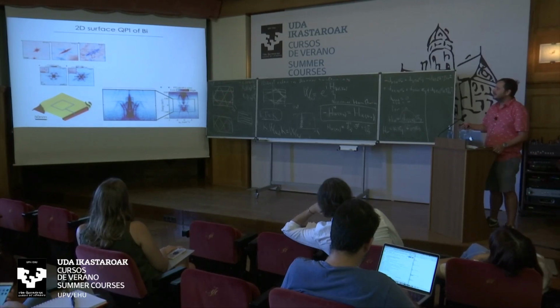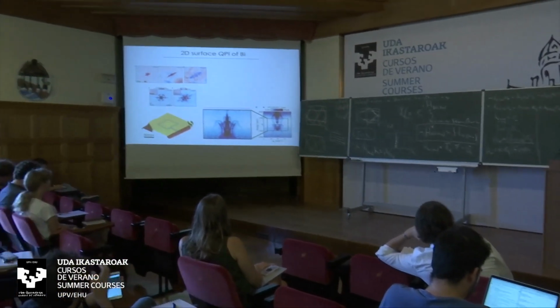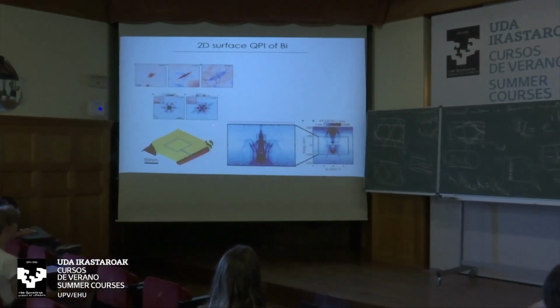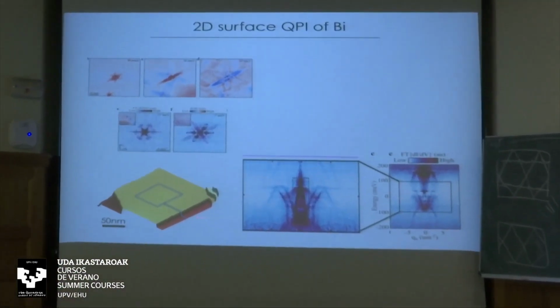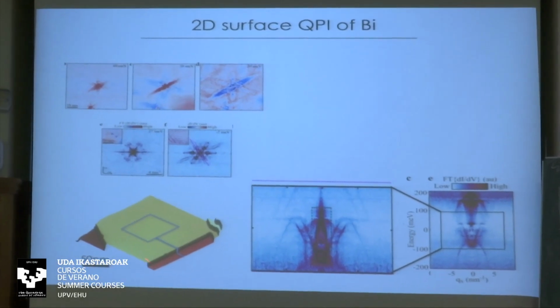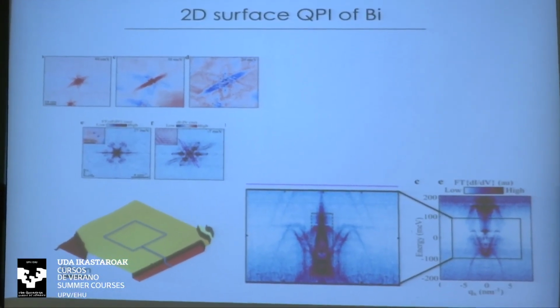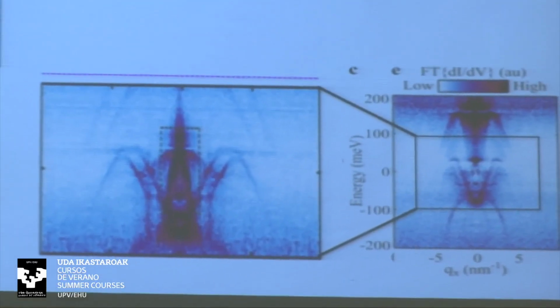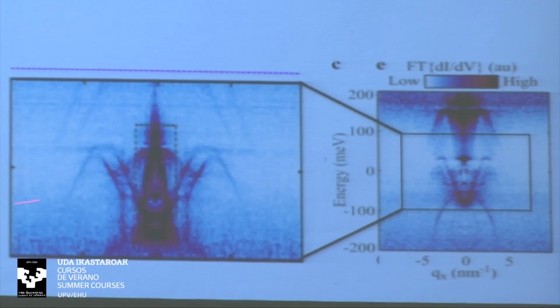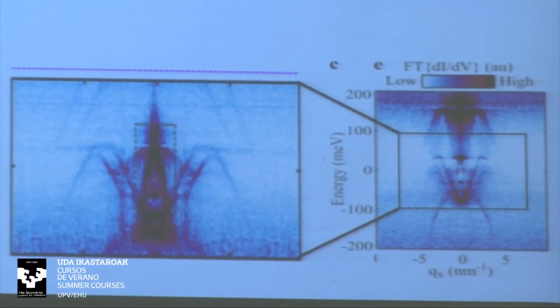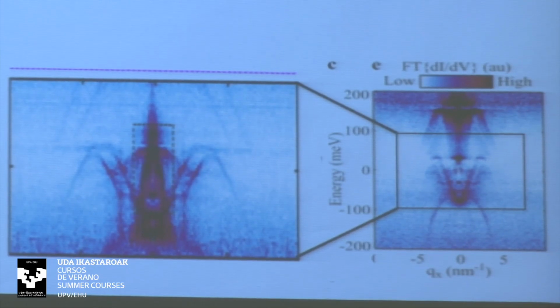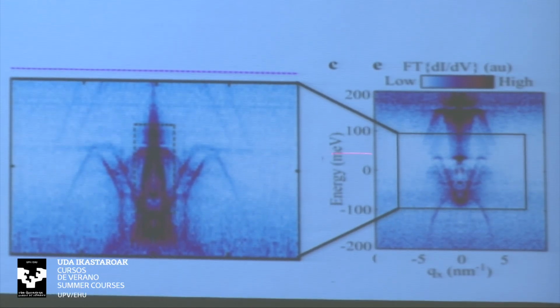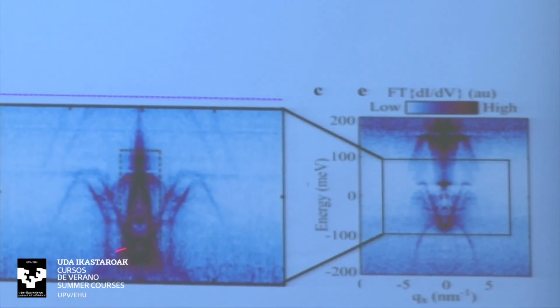One thing we can do is, of course, compare the gamma M direction of this QPI pattern to the gamma M direction that we measured by measuring this line cut from the step edge. And you see the similarities between the two. There are still some differences in the intensities because these are different scatterers. So a step edge scatters some states more, and the point impurity scatters others. This all goes into this matrix element that we didn't take very careful consideration of, but this can give slight differences in intensity, which are quite interesting in their own right.